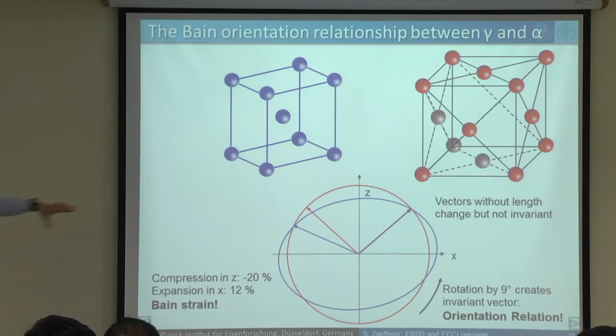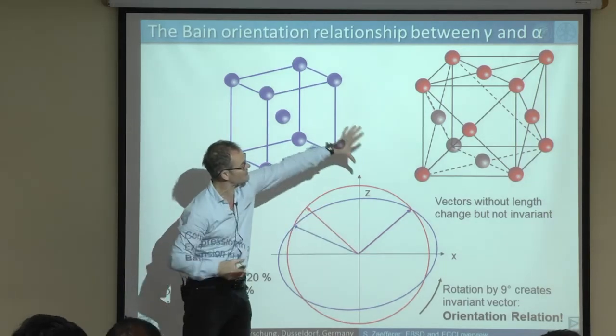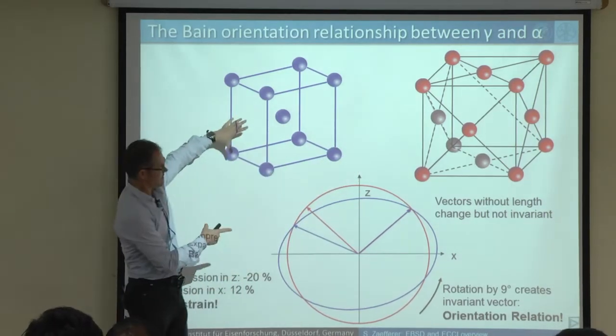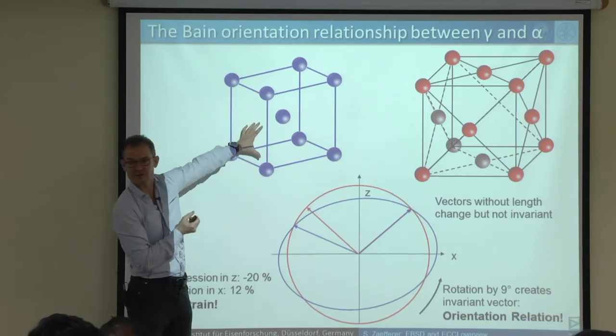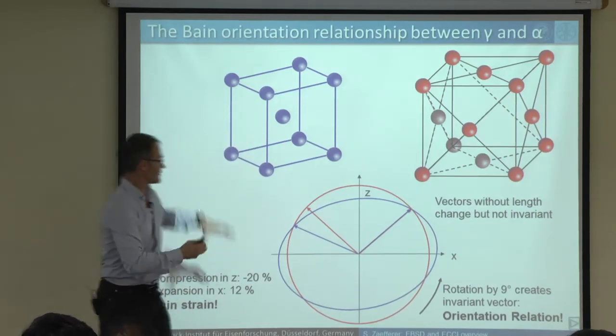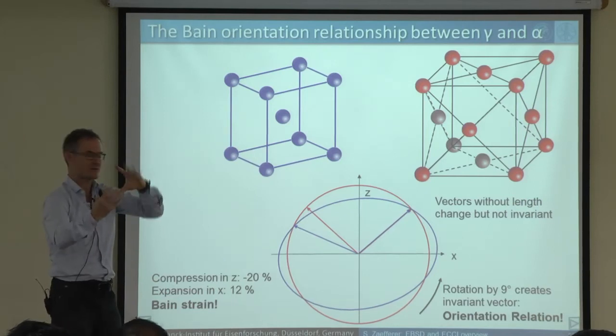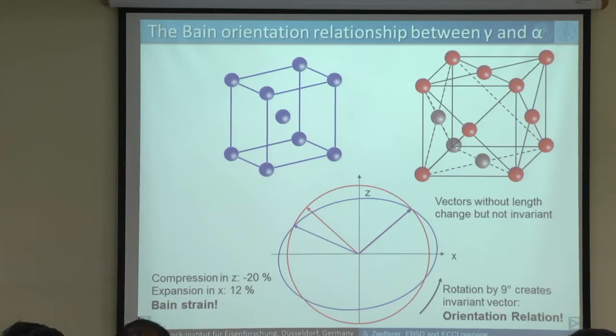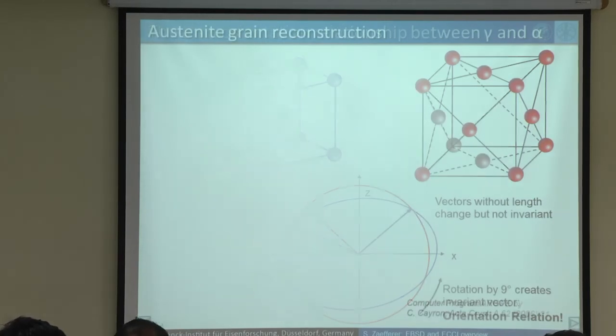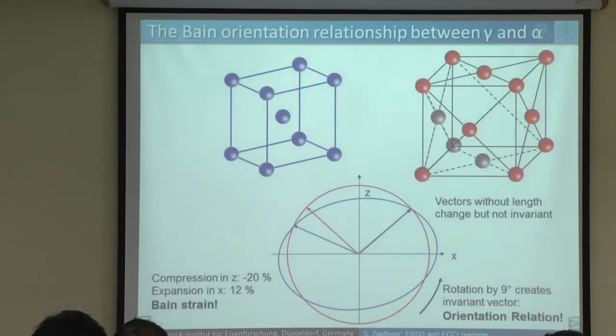But what you can calculate is you need a 9-degree rotation of the crystal lattice of austenite to fit well in certain directions with the crystal lattice of BCC. And that means, so you first have this compression and then a 9-degree rotation, and that means you get an orientation relationship between this one and this one, which is actually in this particular case called the Kurdyumov-Sachs orientation relationship. It's this 9-degree rotation about certain axes. This is all you need to know for the moment. And if you know that, there's other relationships which you can also calculate and display like that, but for the moment just keep it with this.